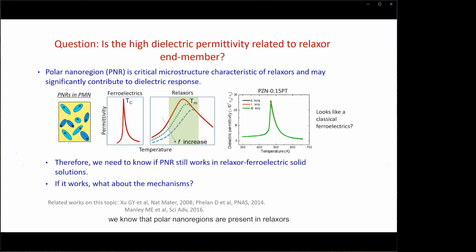We know that polar nanoregions are present in Relaxors such as PMN, as shown in this figure. And the switching of polar nanoregions under electric field could contribute to dielectric response. Generally, in Relaxors, due to the polar nanoregions' contribution, there could be an obvious frequency dispersion of dielectric response. But in Relaxor piezoelectric solid solutions with MPB composition, as shown here, the frequency dispersion is very small and it behaves like a normal piezoelectric material. Therefore, we need to know if polar nanoregions still work in Relaxor piezoelectric solid solutions, and if they really work, we have to know the mechanisms.